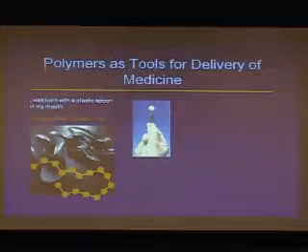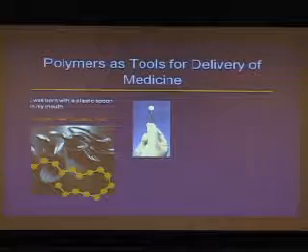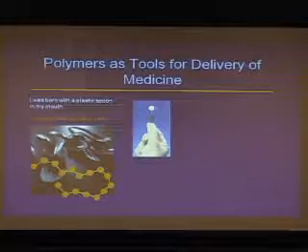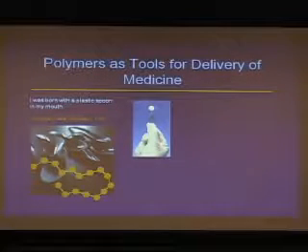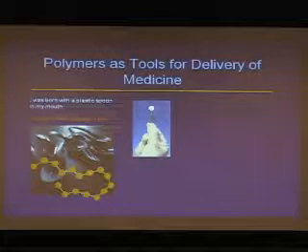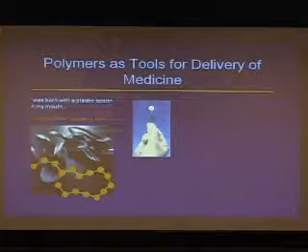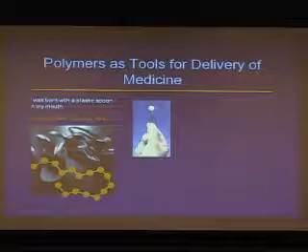And one thing that you can do with certain kinds of polymer materials is fashion them into devices that can be used in the body. So this is an example of a material that's both biocompatible. It's a polymer that if you implant it in tissues, it provokes very little response from the tissue around the implant site. And it's biodegradable, in that it's been designed of polymers that have structures that look like this, but the linkages between the molecules are unstable in water or unstable in the body.